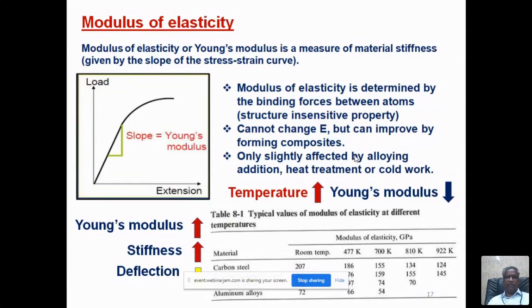If you know, by doing heat treatment or by changing the microstructure, Young's modulus will not change. That's why if you see the Young's modulus of steel, for all the steels it will remain almost the same, whatever the steel it is. Even if it has a different microstructure, the modulus is almost the same. It is around 207 gigapascal, 200 to 210 GPa. That is the steel.